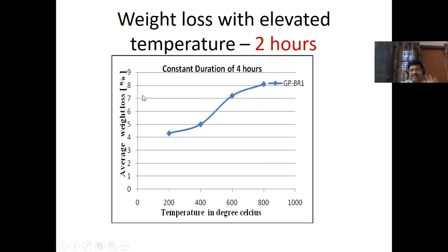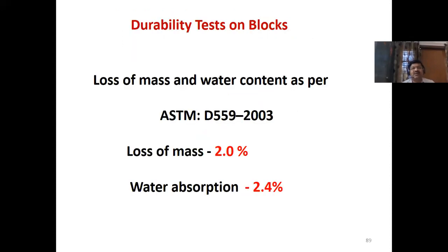I want to draw your attention to the fact that burnt brick or concrete blocks will disintegrate after 400 degrees. They cannot exist, but geopolymer can sustain up to 800 degrees Celsius. We could not go beyond 800 because we don't have the equipment. So only 8% loss. We can conclude that geopolymer is highly resistant to temperature. Next, the durability test, for which we used the ASTM code. Water absorption is 2.4% and mass loss is just 2%. That means it is very durable.